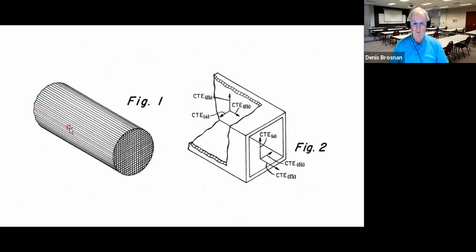His figure 1 shows a typical honeycomb ceramic. Okay, so you can see it has an axis of symmetry in the long direction, typical of an extruded product, and it has open cells in here. Of course, these fired devices are used as automotive catalyst carriers, and so they're used to clean up the exhaust gases in your car, particularly to get rid of hydrocarbons and carbon monoxide. So they're extruded, and his figure 2 shows a diagram of a square cell in this particular case. He's trying to illustrate that we get different coefficient of thermal expansion, CTE values, in different directions. The one that's the most important is in the direction of the extrusion, in the long direction of the device. Okay.